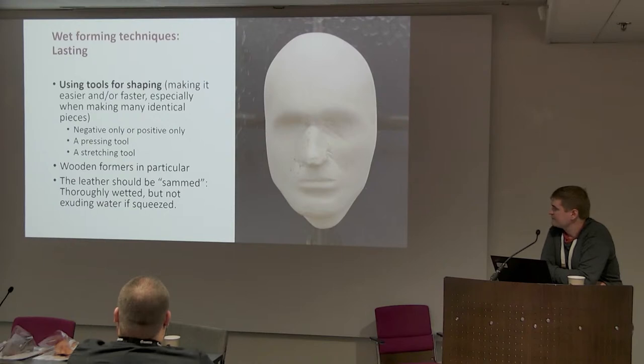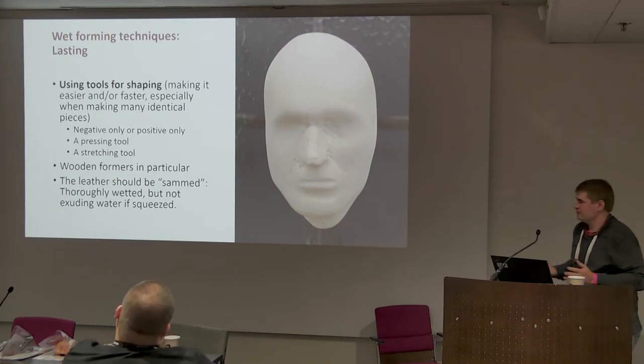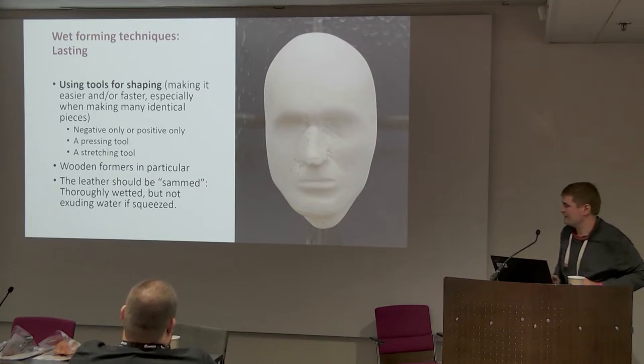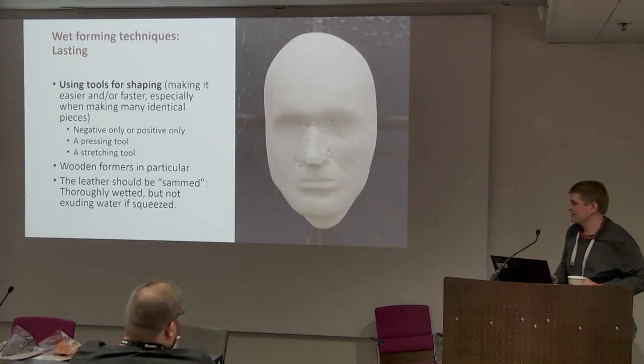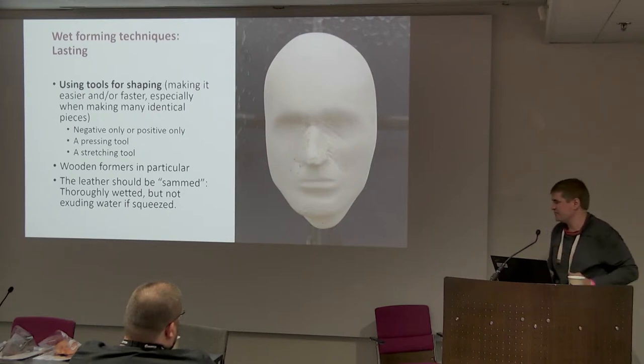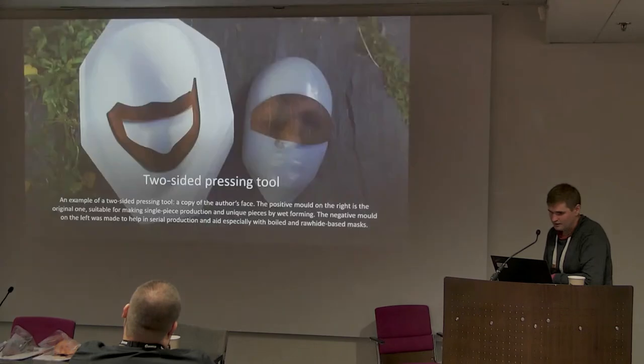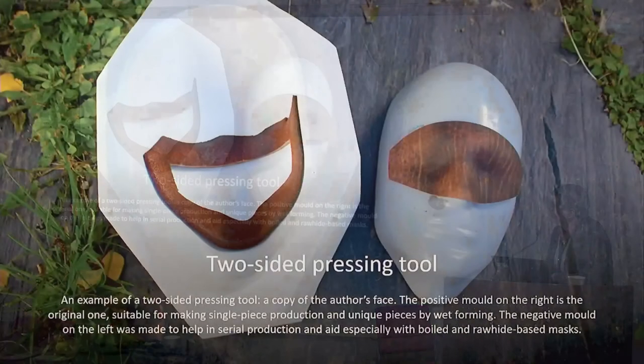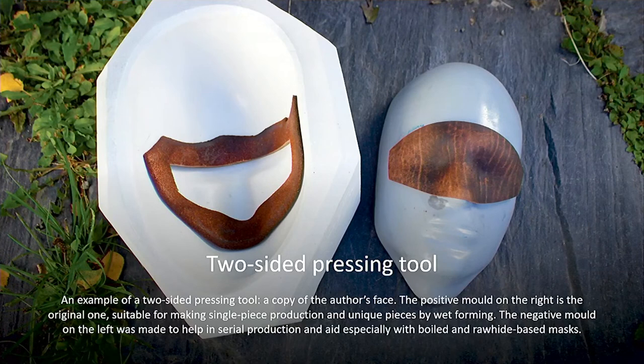A word that is coined sometimes in this context is samming. So the leather is thoroughly wetted, then the moisture is allowed to soak in and even out. So it's not so wet that it exudes water when squeezed, but wet enough so it has good malleability and moldability. And here's the same mold a bit improved, so I made the second half of the mold, and so I could really use it a bit differently than with just the one half.